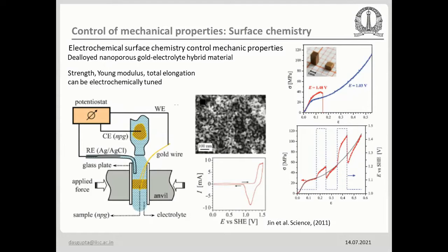What you can see on the right hand side, the blue curve shows a large extent of ductility, and the red curve shows that it is kind of brittle. And how can you get it? You can get it by electrochemical reversible oxidation of a nanoporous gold. So what it is, a nanoporous gold sponge, like it is shown in the SEM image.